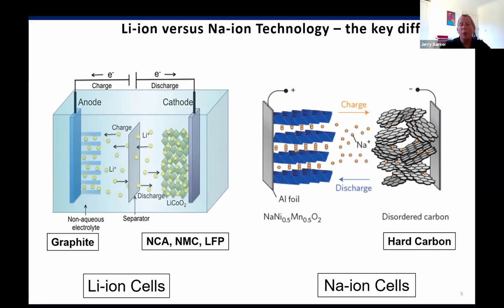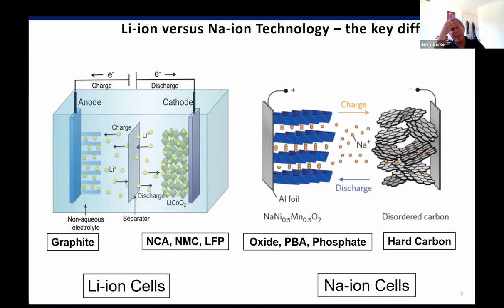For us, we can't use graphite on the negative side, so we use hard carbon, a disordered carbon, that runs in a similar kind of specific capacity range to graphite, but with a slightly sloping voltage profile. On the positive side, this is where you differentiate the different sodium ion chemistries. So you can use oxide, you can use things called Prussian blue analog materials, which are fairly interesting. I'll give you a bit more information on that in a second. And also, just like lithium iron phosphate for lithium ion, we've got the possibility of using phosphate materials or polyanion materials.